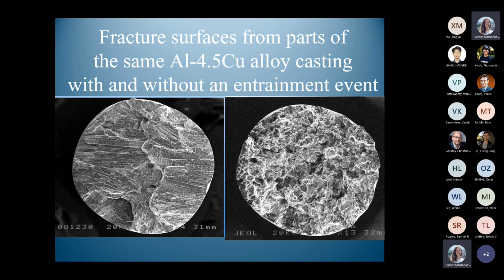whereas this is from the same casting. It's just that at this part of the casting, there was a big back wave and a big splash, and big bifilms were formed. At the other end of the casting, that happened to fill nicely. And so this part of the casting has all the small population of bifilms that were in the original metal that was before it was even poured. And this is the